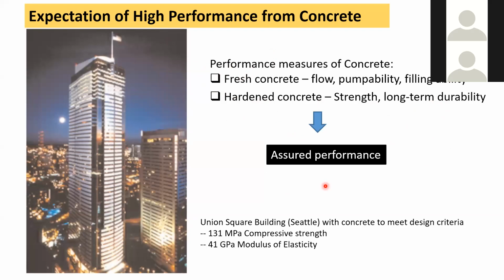I'll just give you an example of where performance found its way. This is the Union Square building in Seattle, where concrete strength was prescribed. It's not a small value, 131 megapascal compressive strength, but they also prescribed a modulus value, a minimum modulus of 41 GPa was specified. So this is one of those early instances where performance started getting specced into our requirement for the concrete.